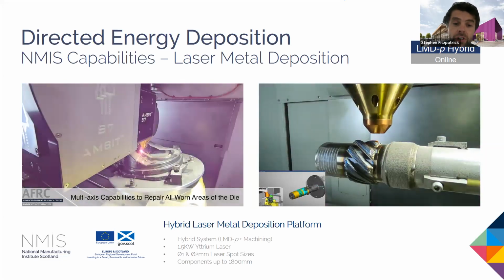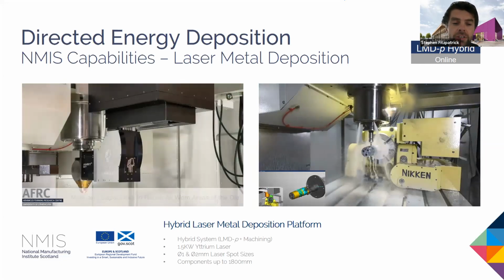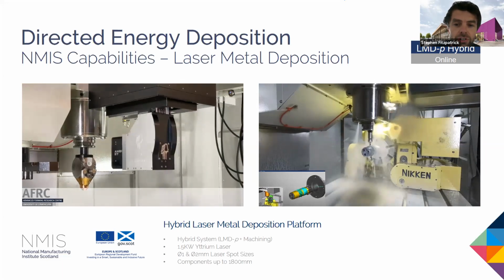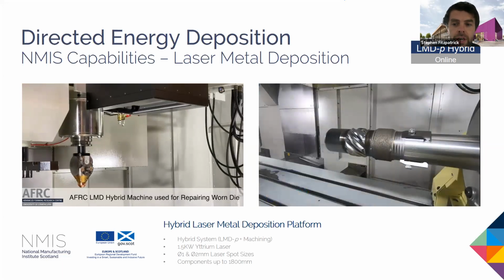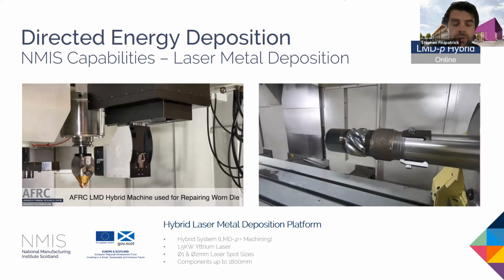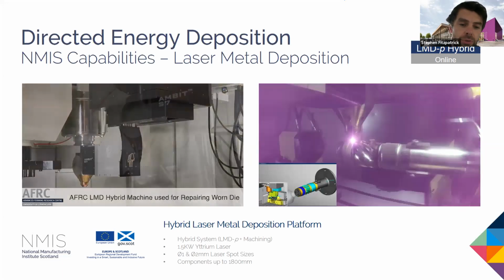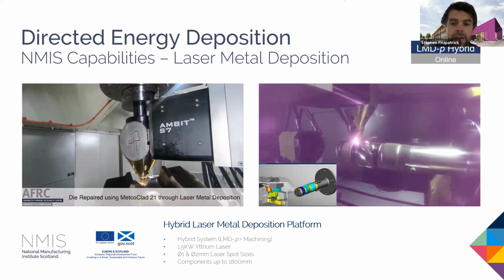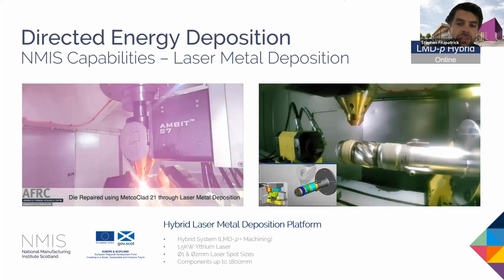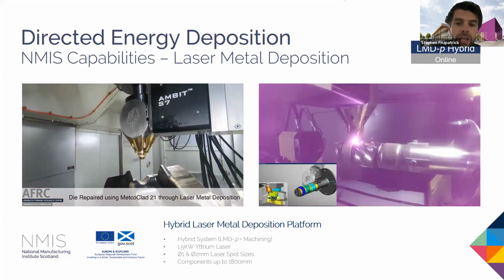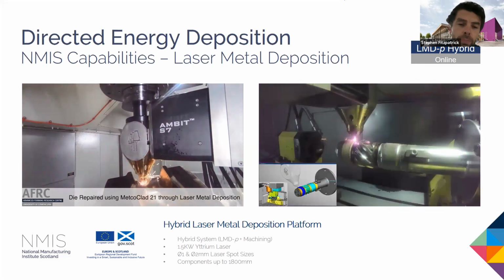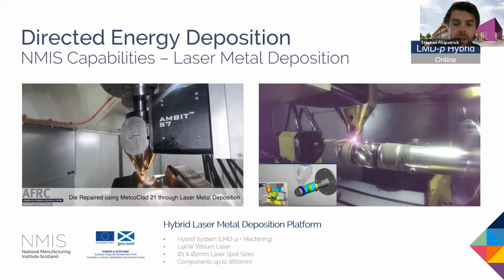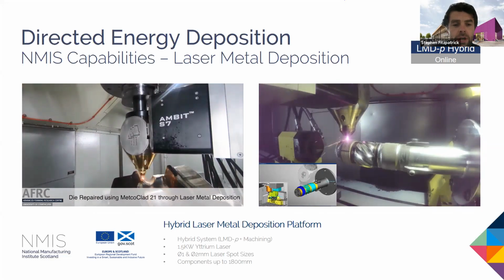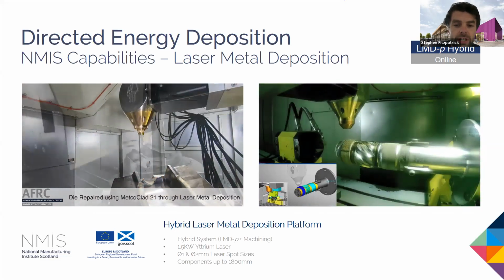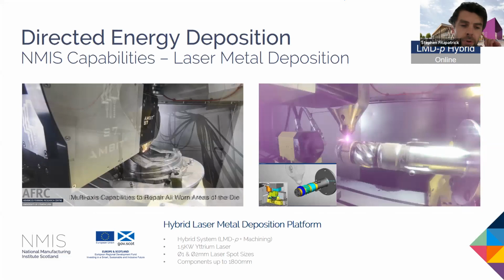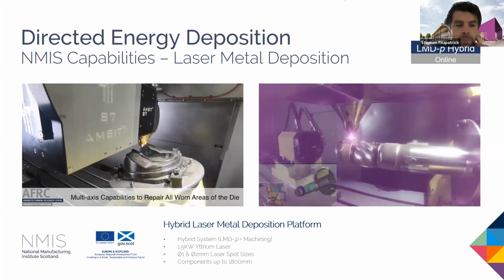You can get benefits such as lower dilution, faster cooling rates, which give you a finer microstructure and lower thermal distortions. It's also quite an accurate process, so you can get close to net shape, so near net shape components from this. However, the deposition rates are lower than arc-based processes, and also powders bring some challenges with them as well. So this is a process that we've been working on for around 6 years, and we've carried out a number of projects in this application area.